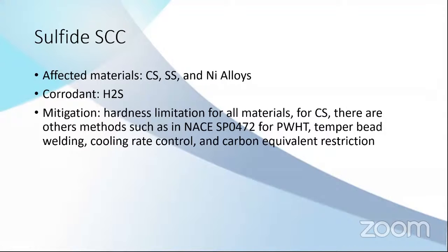Limiting the hardness is almost the same as limiting the strength. So for all materials, when the hardness level does not exceed certain numbers, it can be considered resistant to sulfide stress corrosion cracking. For carbon steel, there are many mitigations other than hardness limitation, like post-weld heat treatment, temper bead welding, cooling rate control, and restriction of carbon equivalent.